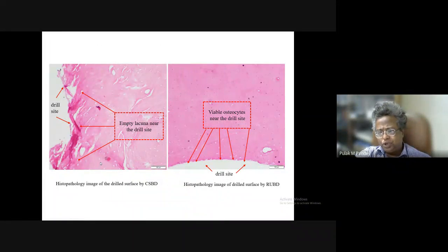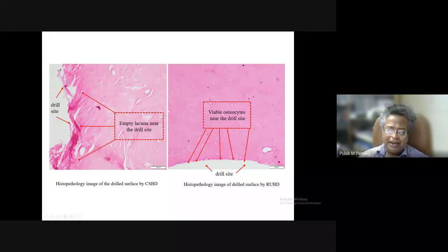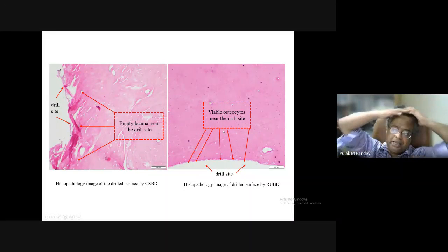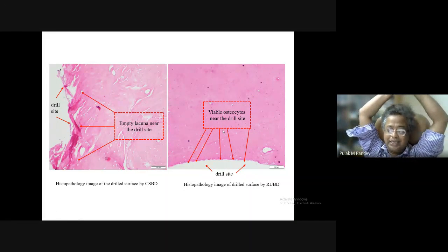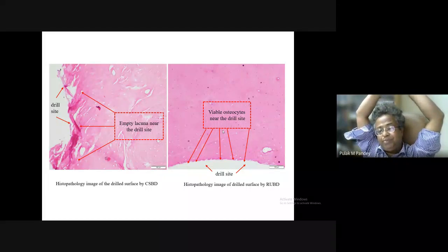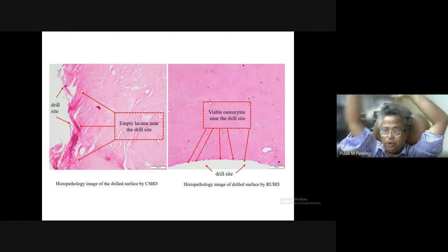This is called a histopathological study, which we did at AIIMS. Once we do it with RUBD, you will find that the drilling site is very smooth, and all these red dots which you are observing here give you evidence of live cells even after 3 months of the hole being drilled.